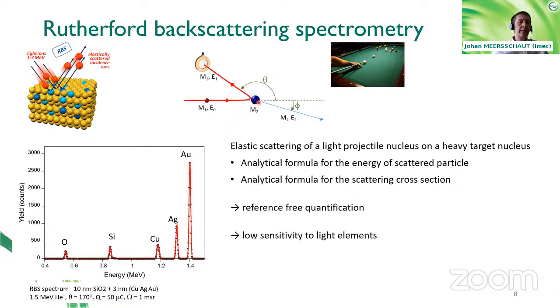And in that specific case, the elastic scattering will lead to a backscattered particle, which can be detected, for example, in a semiconductor detector. The advantage of such an experiment is that the scattering, both for the energy as well as the probability of the scattering, are fully determined by classical theories as you would apply to estimate the scattering on a billiard table. So the heavier the particle on which you scatter, the higher the backscattered particle energy will be. And this is also what we see here on the right.